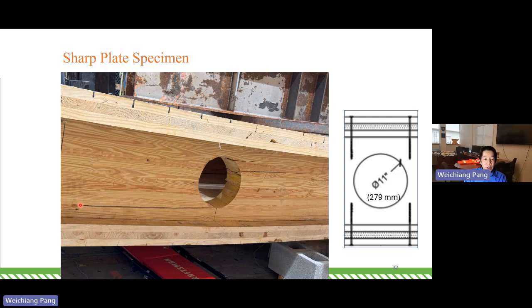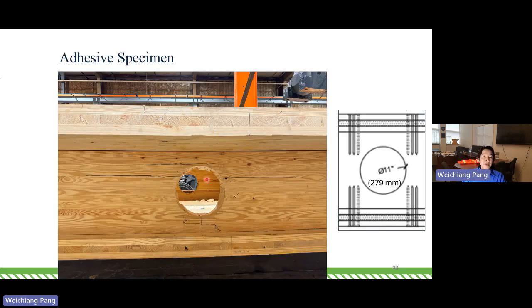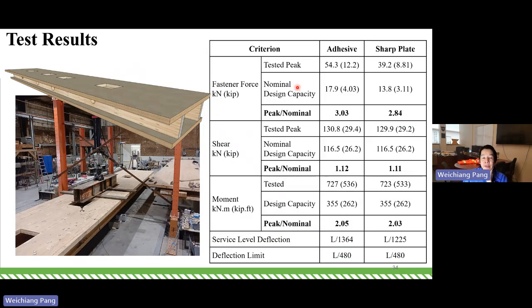And then the shear crack goes all the way and meets up with the finger joint of the glulam lamina here and all the way here. If we get to redesign it again, I will recommend we put more reinforcement around the opening, whenever you have a transverse opening, to limit this shear crack. Very similar for the other adhesive specimen using Simpson screws, we also see a similar crack form near the access hole opening, right?